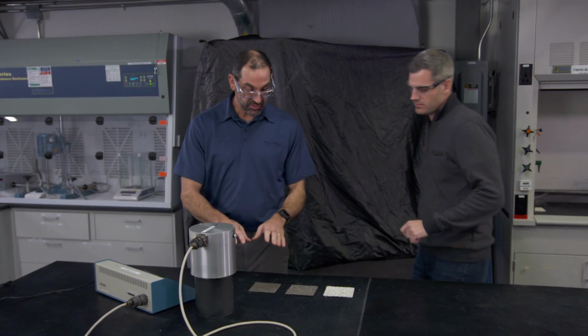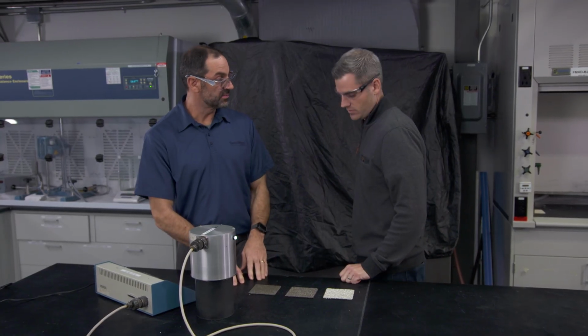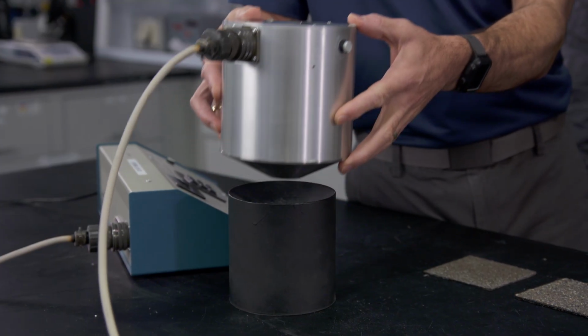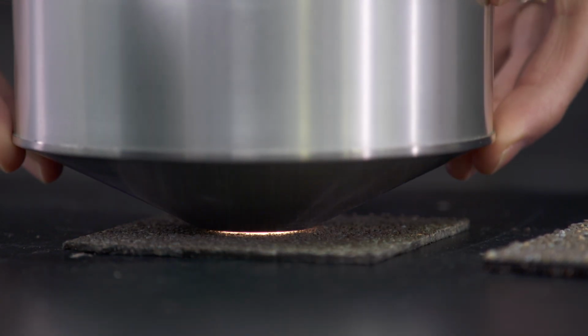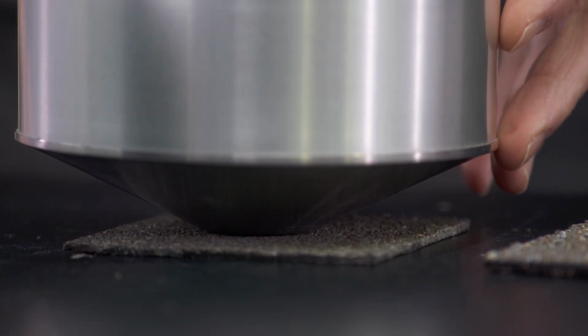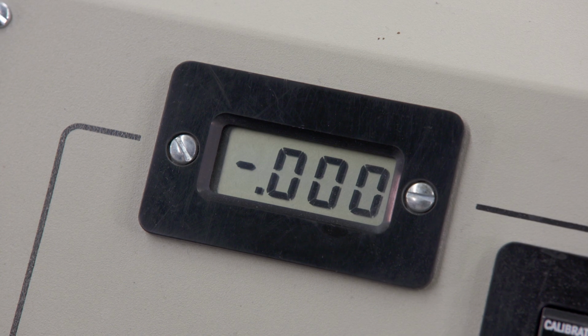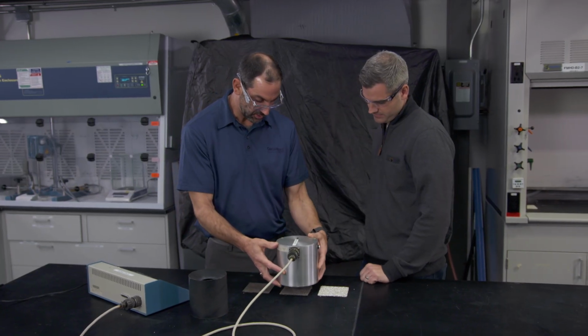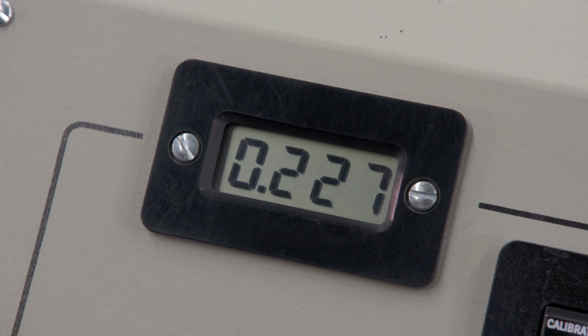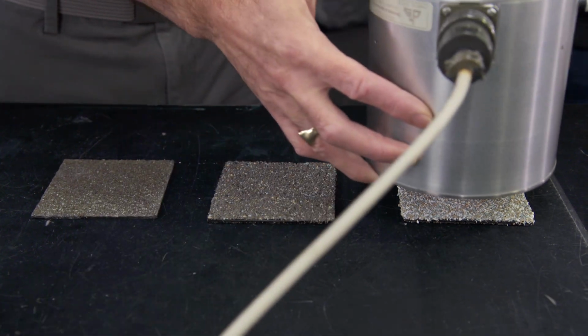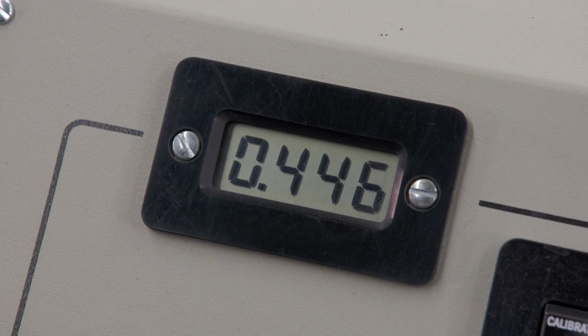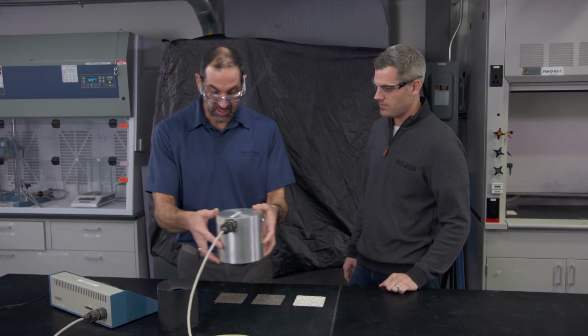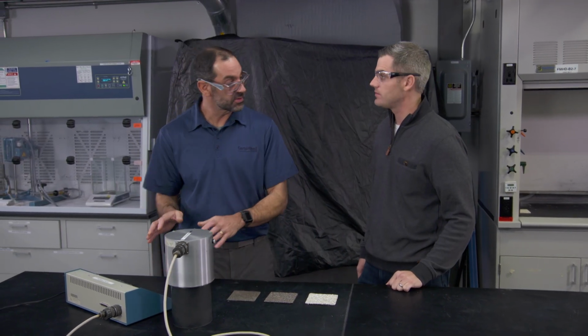So now, Ross, we're going to measure some of our samples to measure the solar reflectivity. What we have here is a solar reflectometer. We'll put this on our first standard shingle. What it does is it sends diffuse light through the sample and then measures the reflection of that light back. Yep, 0.08. 8%. And then we'll look at a solar reflective shingle. So about 22%. And then we'll look at a highly reflective shingle. So this is about 44%. Got it. And this is the one that has the specialized coating. Correct. So this is one test we do, and let me show you some other tests we do.